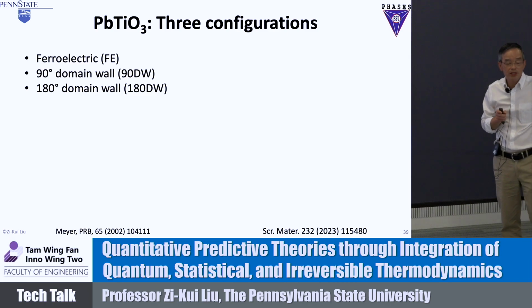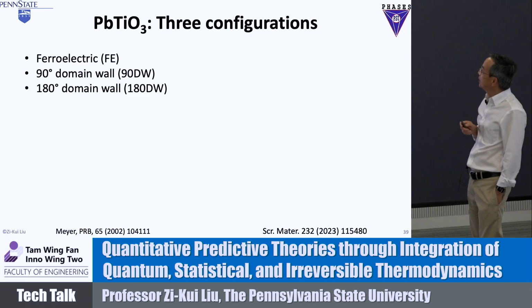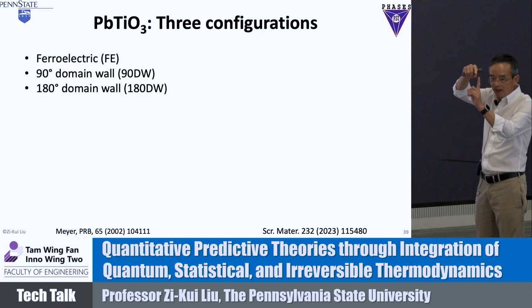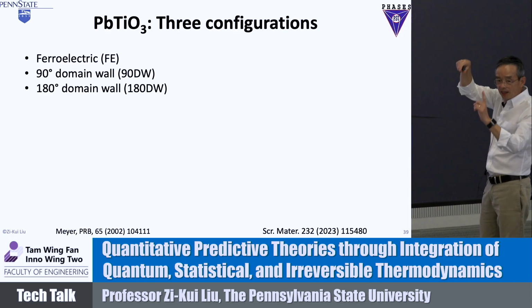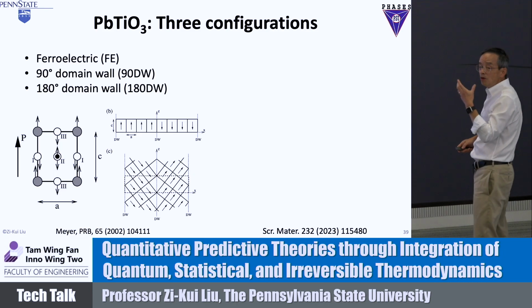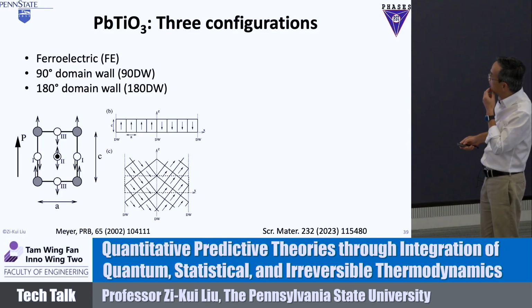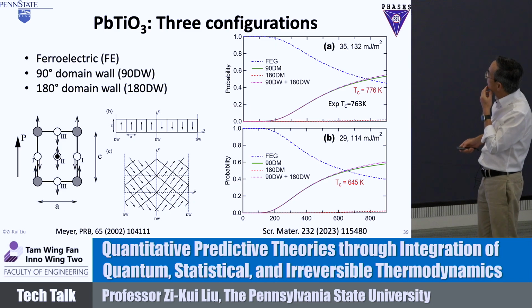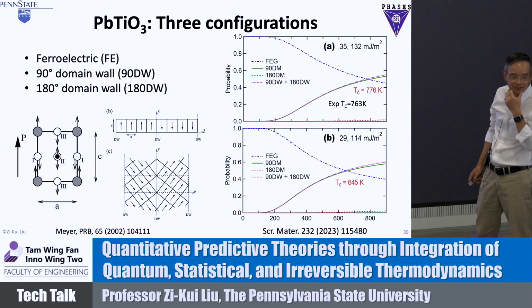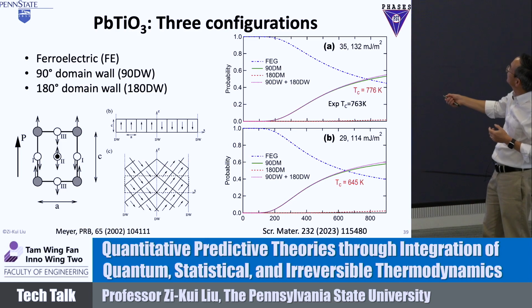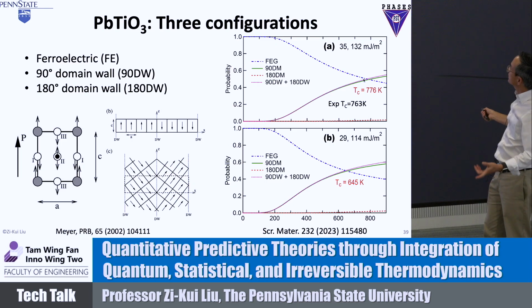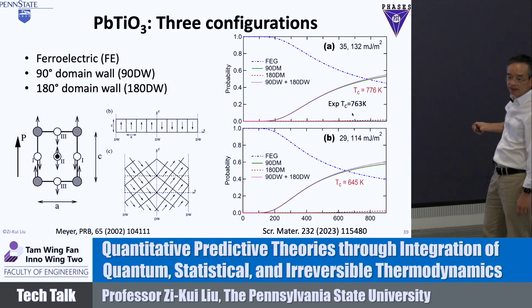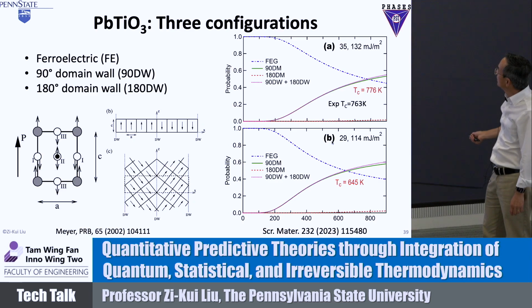It turned out there are only 3 configurations. One of them is ferroelectric, another is a 90-degree domain wall, because the polarization goes 90 degrees, and another is 180 degrees. So basically only 3 configurations. We take the data from the literature and calculate the probability. It turned out the literature has 2 sets of data. One of them is from Vanderbilt's group. You get 35. The predicted 50% of the ground state is 776 K, about 13 degrees higher than the experiment. That's the best prediction in the literature ever. I have not seen anyone close to that yet. But if you take another set, is